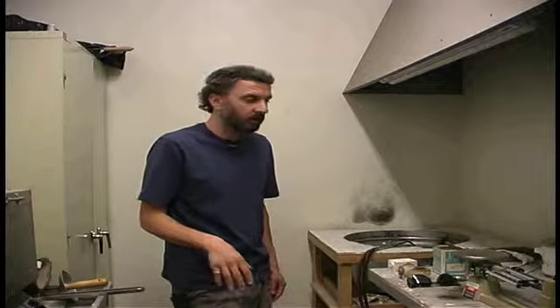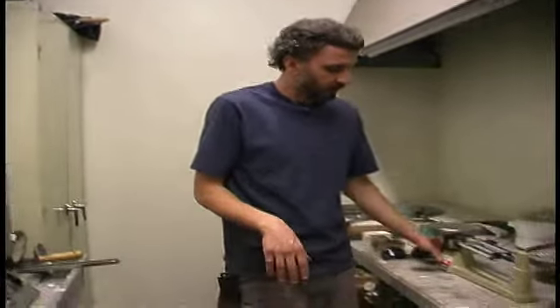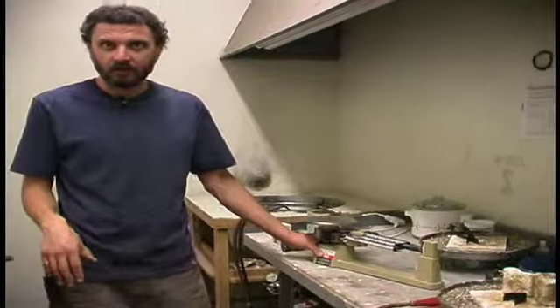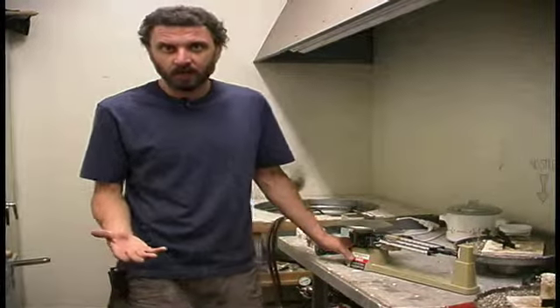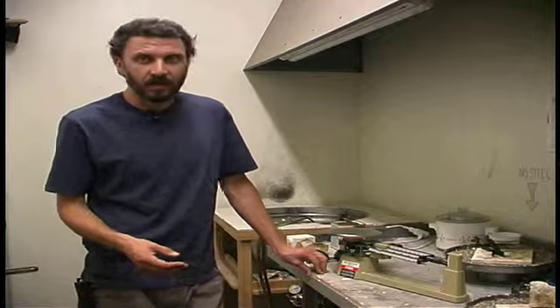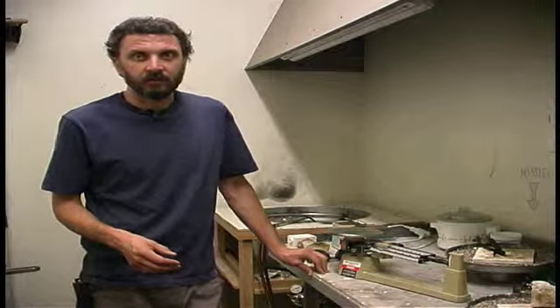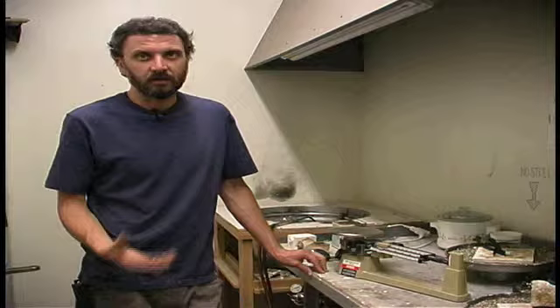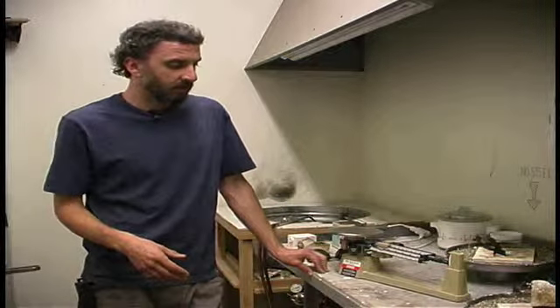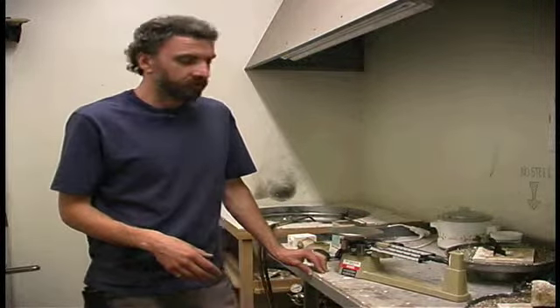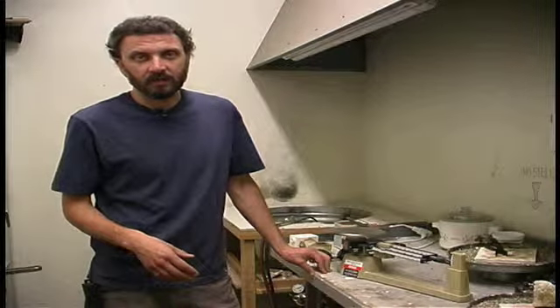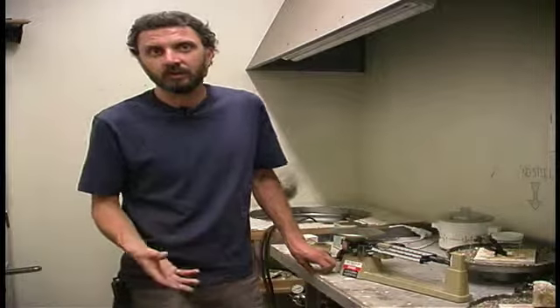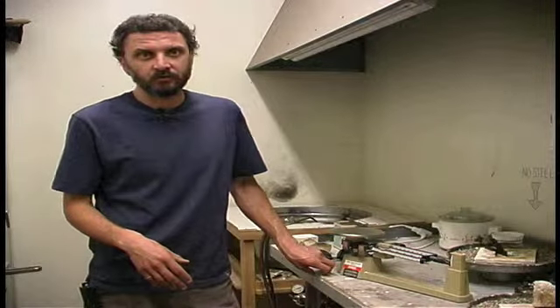So once we reach the proper temperature of 1200 degrees for at least 2 hours, we're ready to cast. What we do after that is take the weight that we've measured in wax, say our weight is 2 grams in wax, and multiply that number by the specific gravity of the metal. Each metal has a different specific gravity. Our class mostly uses sterling silver, so we multiply that times 10.4. So a wax ring of 2 grams is going to be approximately 20 grams of sterling silver.